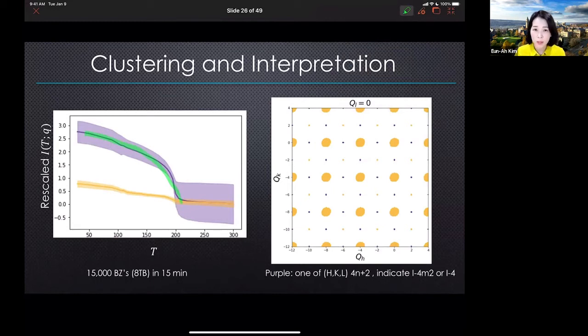These are all Bragg peaks. In this material, the structural transition does not change the size of the unit cell. There are no new peaks showing up. But what you do see here is that all the purples are coming from one of the indices of HKL being not a multiple of 4.